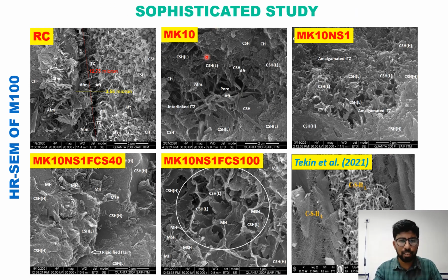Coming to the sophisticated study, in the reference mix we can see AFm of flower petal shape and AFt of needle shape, with a gap at the ITZ. While replacing metakaolin, it has been interlinked and low density CSH has been formed. While replacing the optimum nanosilica, we get the amalgamated ITZ. In the optimum mix, we can see the rigidified ITZ with dense CSH, and we can witness why the strength degraded while replacing 100% ferrochrome slag. This is due to the spiderweb shape of low density CSH, which is a similar pattern to Tekin et al.